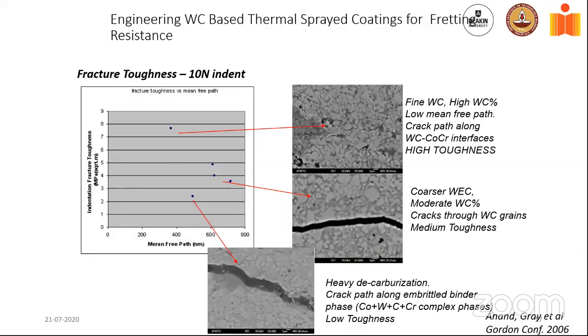Fretting resistance, among other things, is a function of fracture toughness. I can't show you all the data I have on fretting wear properties. That gets into stuff which is proprietary. But what you can see is that for the same composition, by adjusting the process parameters and the equipment used, I can essentially have a fracture toughness change by an factor of 3. So I can go from a fracture toughness of around 2.5 MPa square root meter to around 8 MPa square root meter. And that's really because of the kind of microstructures that these coating processes have produced.